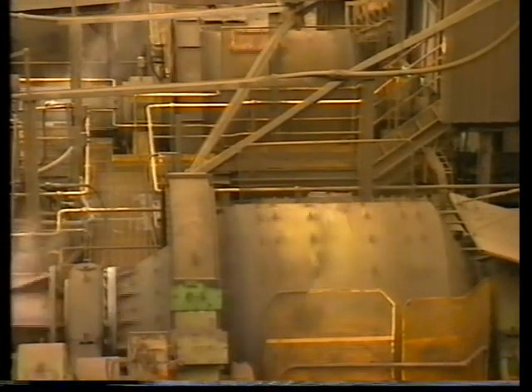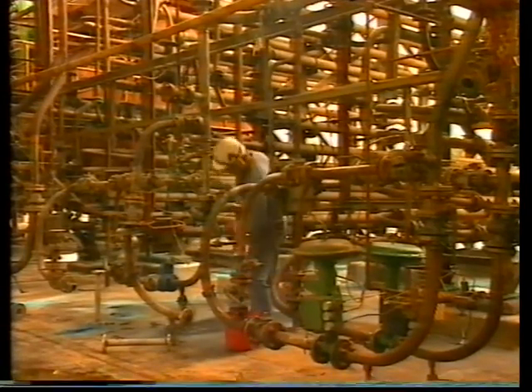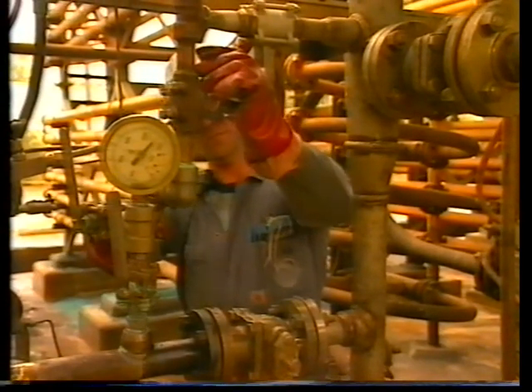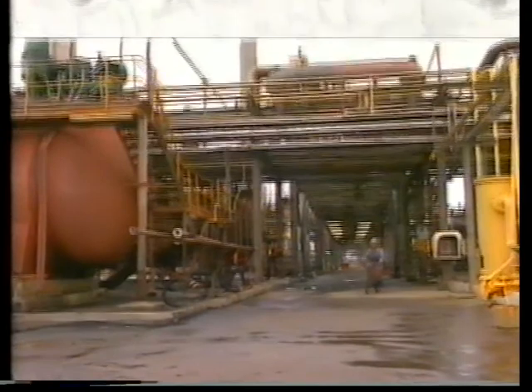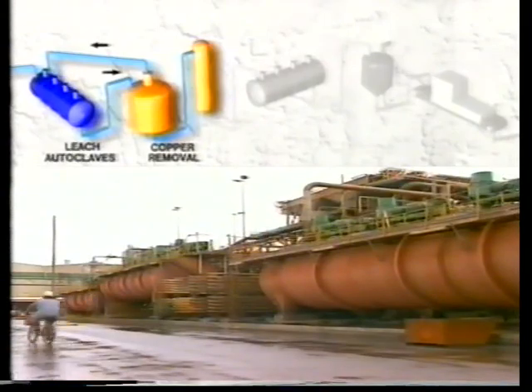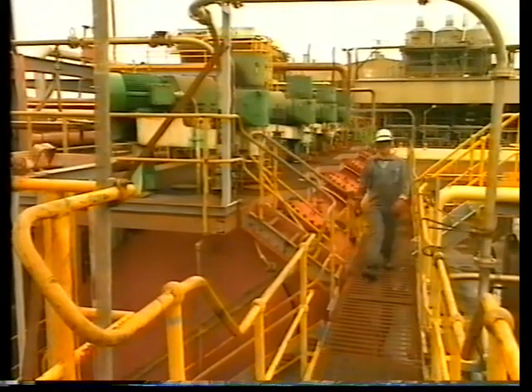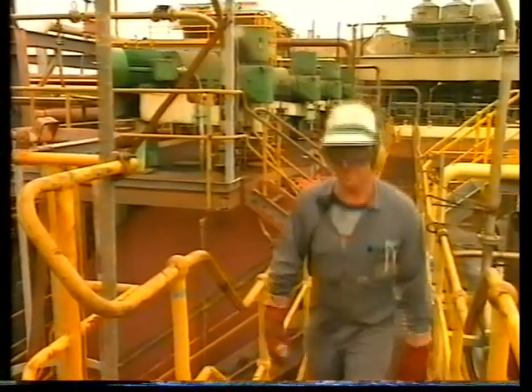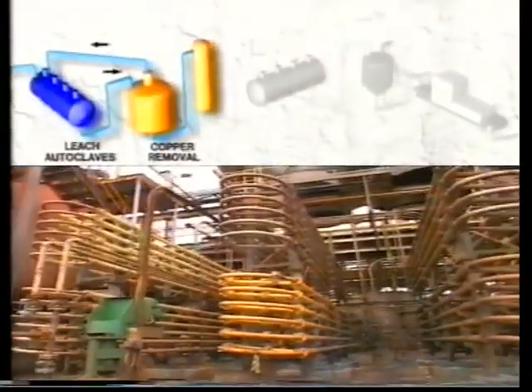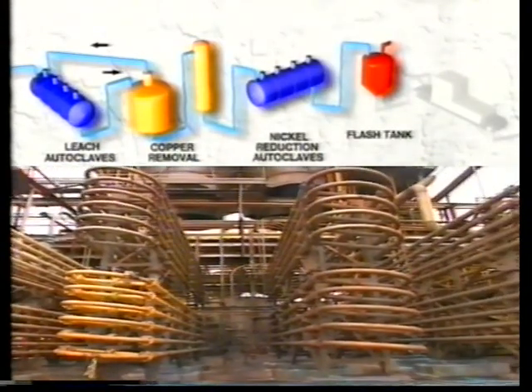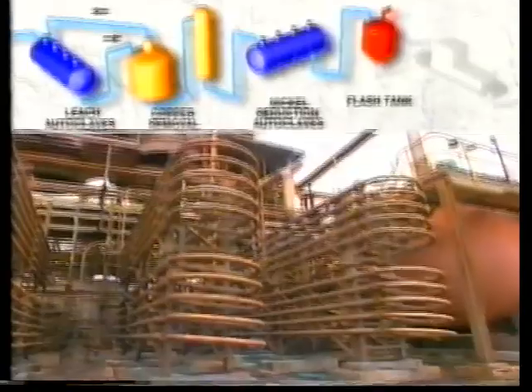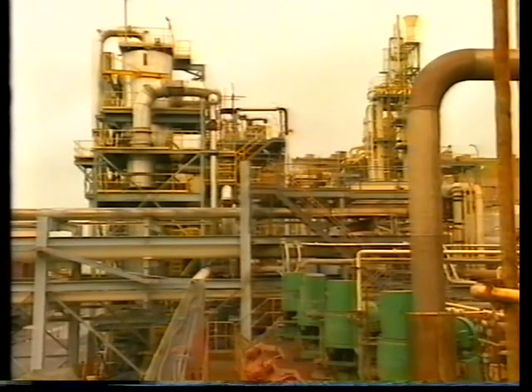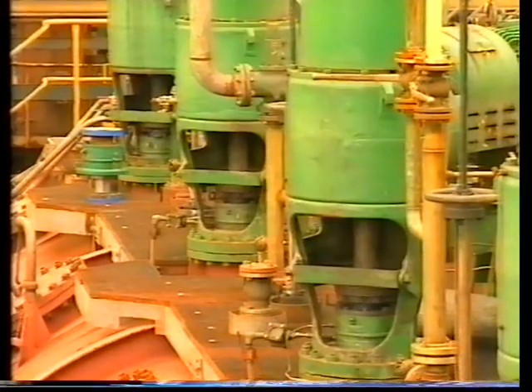First, the matte feed is finely ground and pumped through a series of leach autoclaves, where under high pressure and temperature, it reacts with air and ammonia. This leaching process dissolves the valuable minerals, nickel, cobalt, and copper, but leaves iron and other impurities as an insoluble residue, which is removed. The leach liquid is first processed by boiling under pressure to remove the copper. The now copper-free liquid is then treated by an oxidation and hydrolysis process, and then fed back to the reduction autoclaves, where it is treated with hydrogen gas, which displaces the nickel.